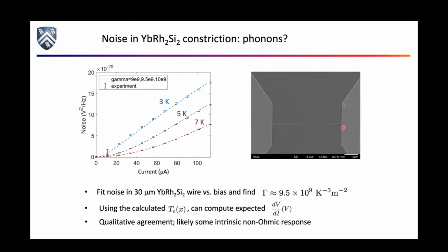Here's the wire. Here's a 30 micron long wire, also very narrow, of YbRh2Si2 between contacts. The data points are on here, and this is basically the noise in this long wire versus bias current. We can interpret it through that model I just showed you, and the only fit parameter for these 3 curves is gamma. So you know everything. The only adjustable parameter you have is the electron-phonon energy loss coefficient.